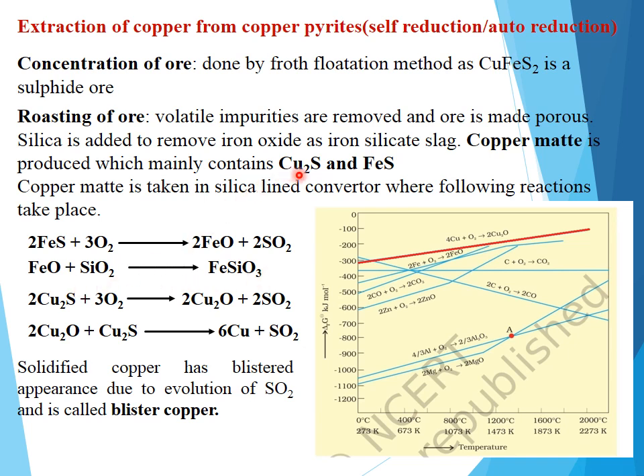Next, the Cu2S left out of the copper matte oxidizes itself. Here this cuprous sulfide is partially roasted or partially oxidized to produce cuprous oxide. Once the cuprous oxide is formed, it combines with the left out cuprous sulfide to produce copper. Here we are not adding any different kind of reducing agent. Due to partial oxidation, you get cuprous oxide. The same cuprous oxide combines with the remaining cuprous sulfide to produce copper, liberating sulfur dioxide gas.